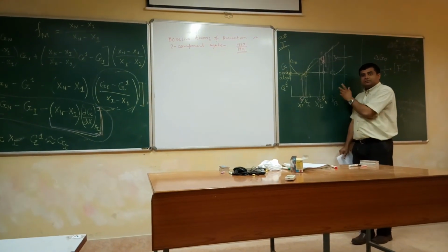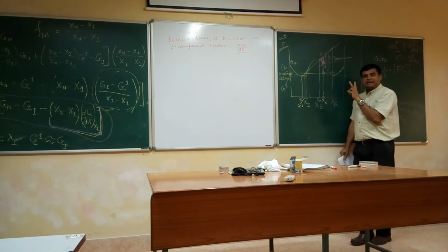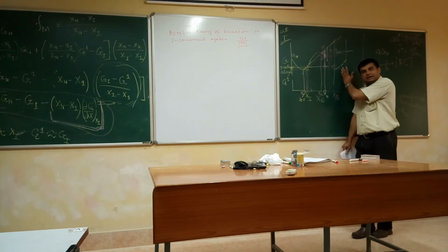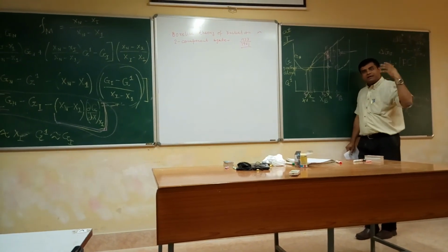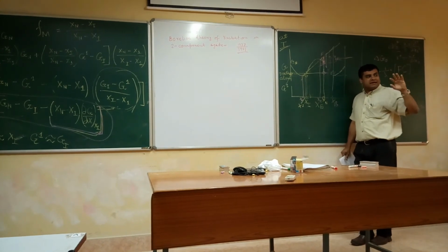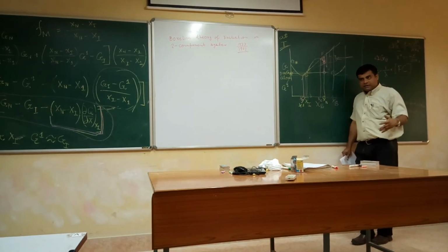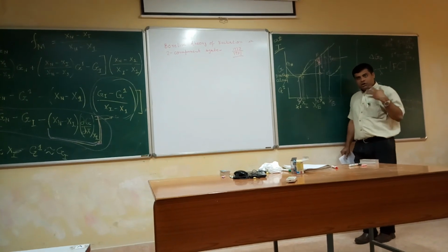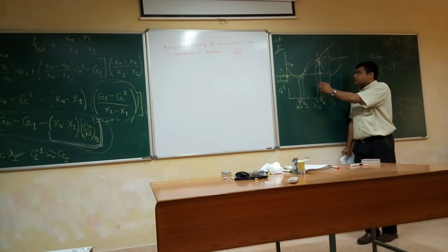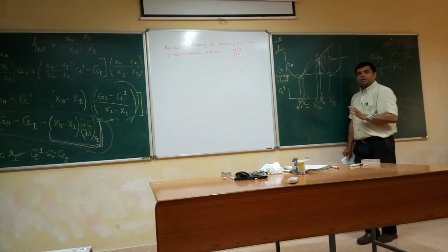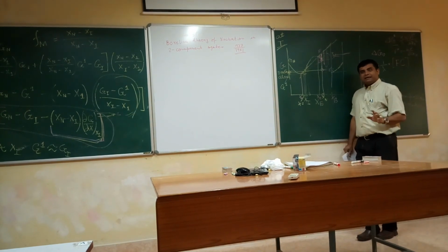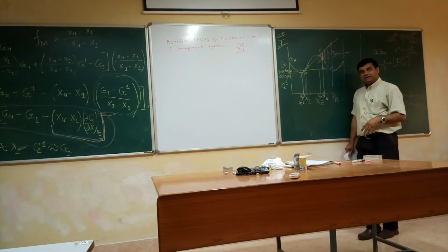In Borelius, here you have two variables, size and composition. Becker did fix the composition and then used the classical nucleation theory to find out R star. What Borelius did is he fixed the size, ignored gamma, and tried to find out for what composition of the embryo the nucleation rate is maximum. Then delta G star is only a function of delta GV.